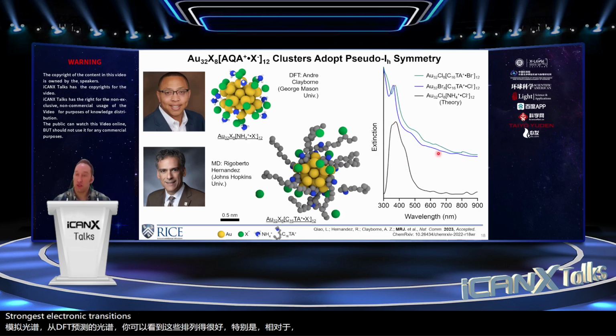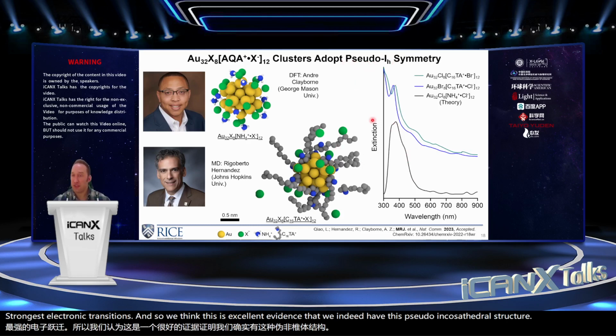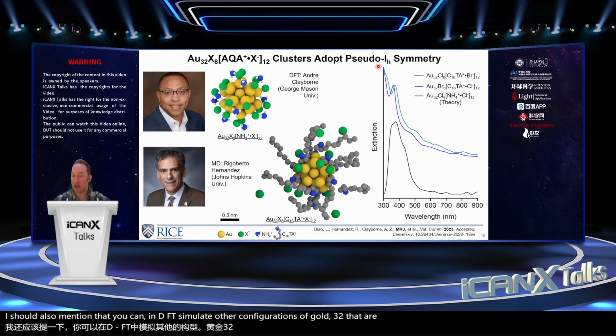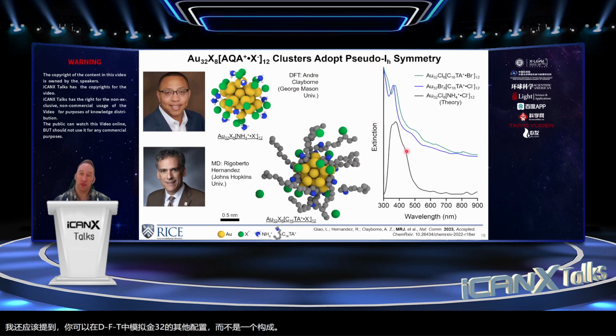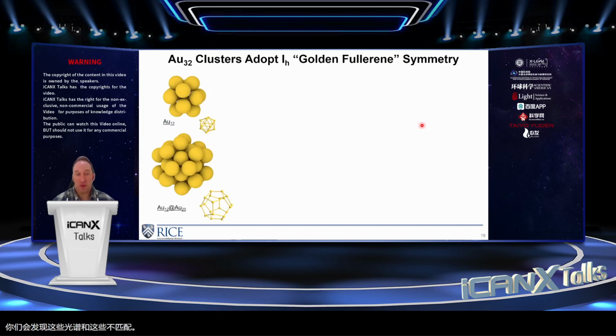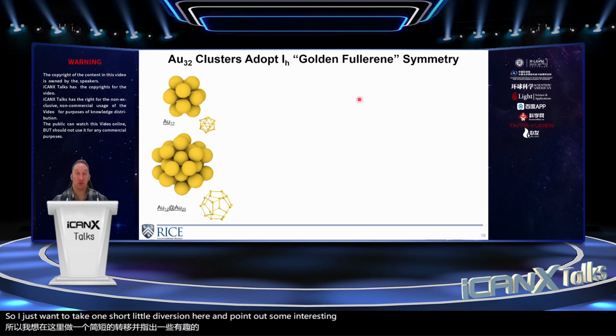And so we think this is excellent evidence that we indeed have this pseudo-icosahedral structure. I should also mention that you can, in DFT, simulate other configurations of gold-32 that are not icosahedral, and you find that those UV-Vis spectra do not match these. So I just want to take one short little diversion here and point out some interesting historical fact about what